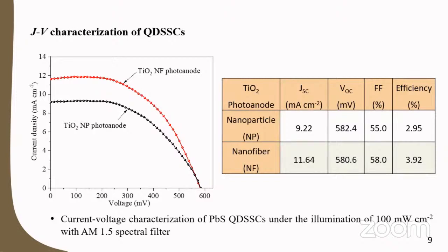Fill factor of the TiO2 nanofiber device has also increased, while overall power conversion of the nanofiber device has increased to 3.92% compared to 2.95% of TiO2 nanoparticle device. Both current density and efficiency show significant enhancement here. This is due to more light captured by quantum dots, as the scattering light extends the traveling distance of incident light.